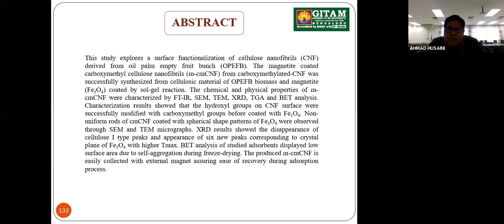Characterization results show that the hydroxyl groups on the cellulose nanofibril surface were successfully modified by the carboxymethyl group, before being coated with ferrum oxide. Non-uniform growth of the carboxymethyl cellulose nanofibril coated with a spherical pattern of ferrum oxide was observed through SEM and TEM. XRD results show the disappearance of the cellulose type 1 peak and the appearance of six new peaks corresponding to crystalline ferrum oxide. BET analysis showed low surface area due to self-aggregation from the freeze drying, and the produced magnetic CMCNF is easily collected via an external magnet, ensuring recovery during the adsorption activity.